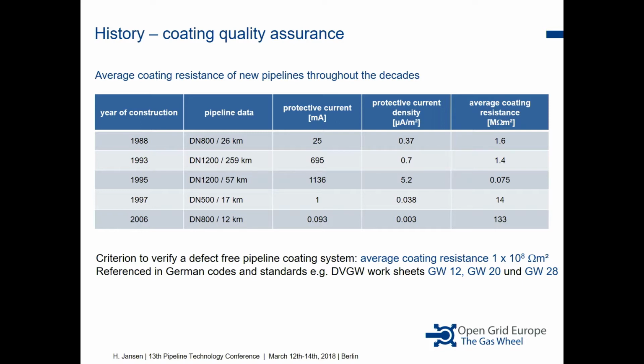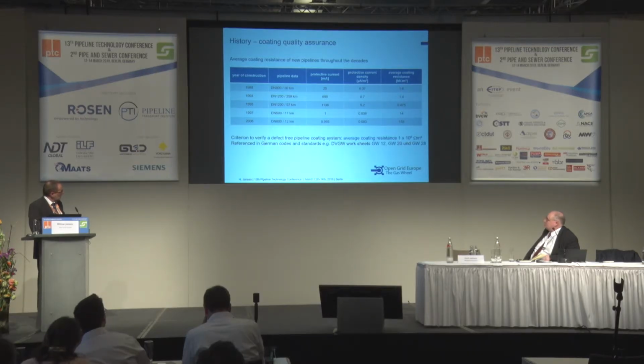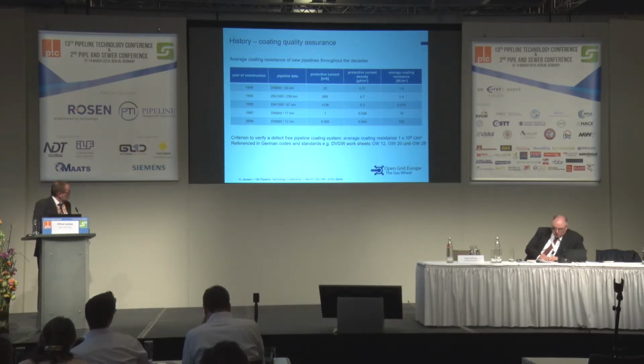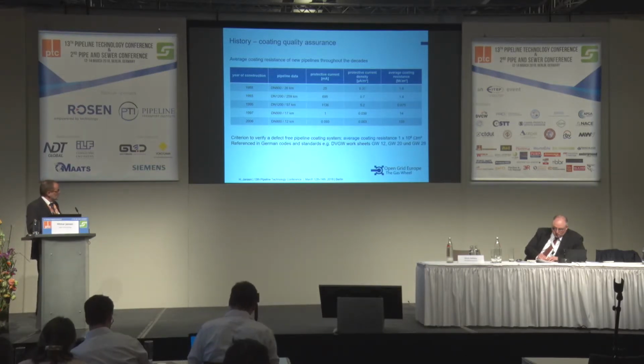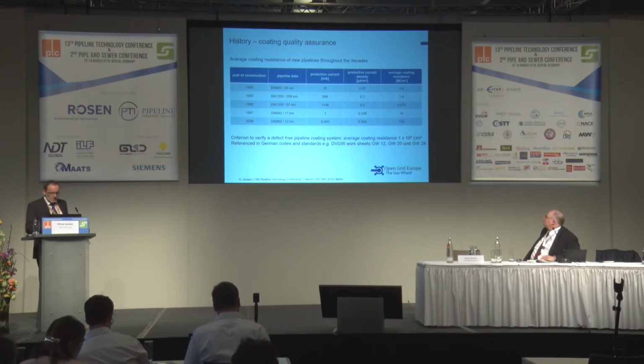With this technology, we could increase the average coating resistance to 10 times higher, so produce more quality. And in 2006, we gave a threshold value of 10 to the power of 8 ohm per square meter, which is now put in German codes and standards from the DVGW. This is also one of our partners here at PTC. They produced the worksheets GW 12, 20 and 28, where we gave this average coating resistance, where we manifested this 10 to the power of 8 ohm per square meter.